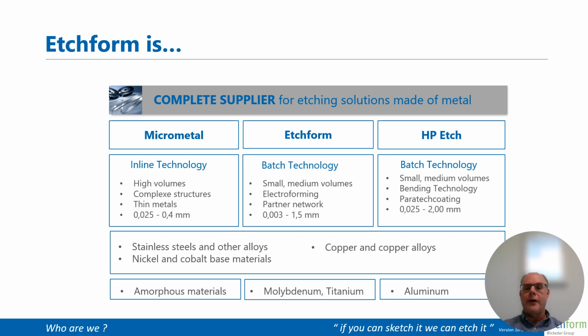Our sister company HP Etch in Sweden, like Etchform, uses sheet etching for small to medium volumes. They are strong in bending of the etched products. Especially for electronics, they can apply Paratech coating, and they are also specialists in etching aluminium. Then my company, Etchform in the Netherlands, can also offer electroformed parts, and we are a specialist in very thin materials, in thicknesses ranging from 3 microns up to 1.5 millimeter. And besides the standard materials, we can also etch difficult to etch materials like molybdenum and titanium.